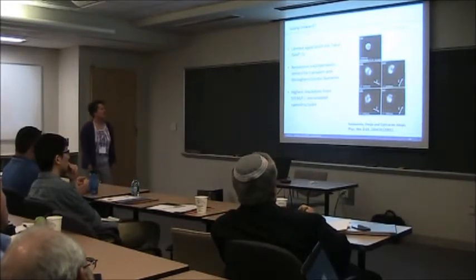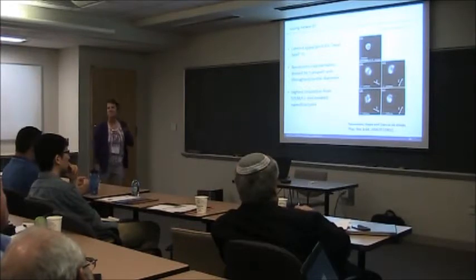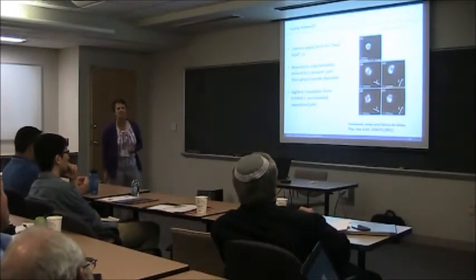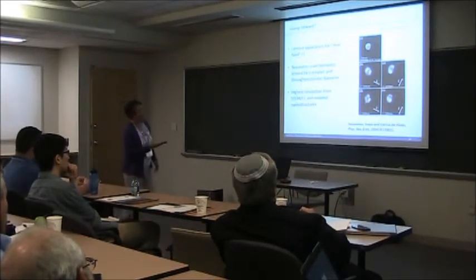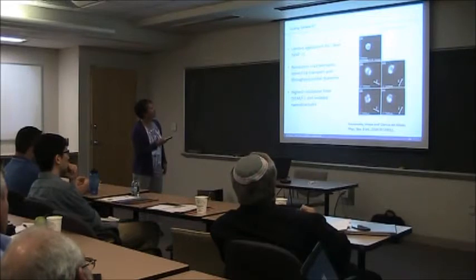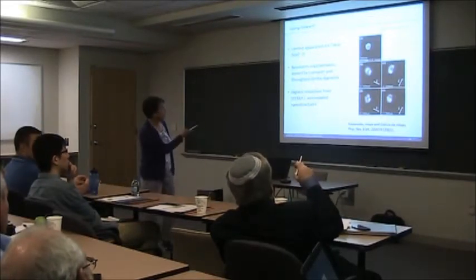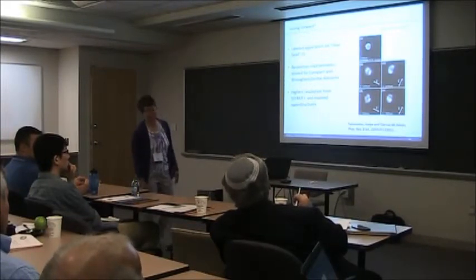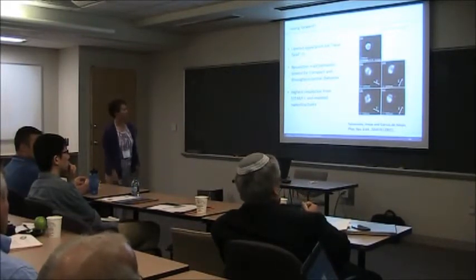I mean, that's pretty impressive, and it's gotten even better since that point, and we're still limited by the size of our probe. The smallest ones I use are about 150 nanometers. I've made it to 100 once or twice, but I usually have to use larger ones. So how big is this structure? 200. So it's a highly limited structure. Yes, absolutely. But there's just a lot of work like this now.